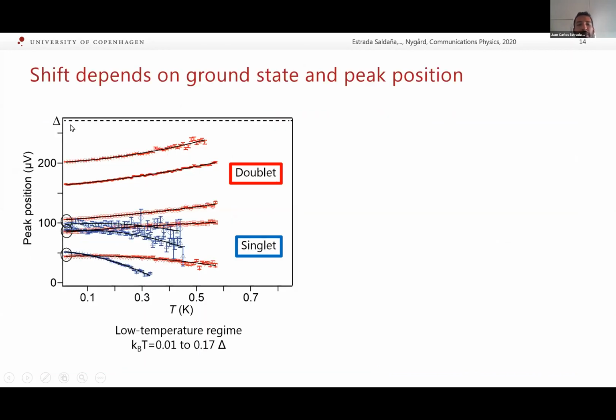So we fit again with the Gaussian to extract the peak position of these YSR states. And this is plotted here, peak position versus temperature. We have in red states which have a doublet ground state, and in blue, those which have a singlet ground state. And we can see two things. The first thing is that the curvature of these curves changes from positive, so shifting towards the gap, to negative, shifting towards zero bias. And we can also see that for pairs of states which have approximately equal initial position, those which have a singlet ground state shift faster towards zero bias with temperature than those which have a doublet ground state.